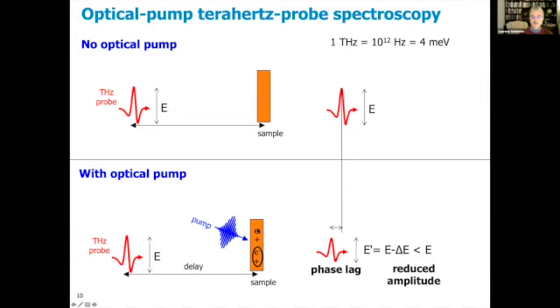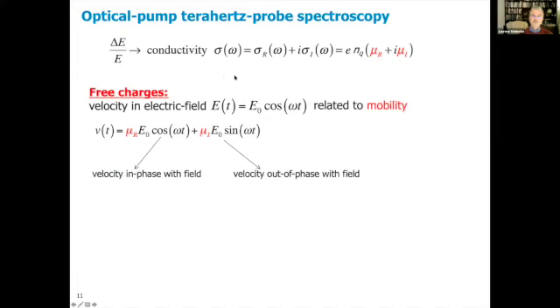Now, if you have free charges, then the terahertz wave, the electric field wave, can sweep up the motion of the charges a little bit, and in that way transfer energy to the charges, and due to that, the amplitude of the electric field will reduce. In addition to that, if you have excitons, excitons enhance the refractive index or the dielectric constant of the material, and that causes a phase lag that reduces the velocity of propagation of the terahertz radiation, and we can also measure that phase lag. So we measure the reduction of the amplitude and the phase lag. And these two things are related to what's known as the real and the imaginary conductivity.